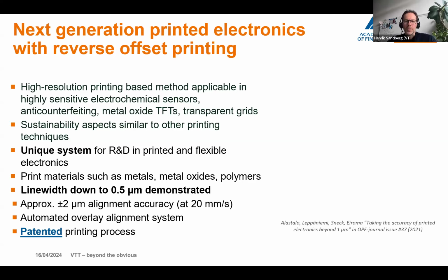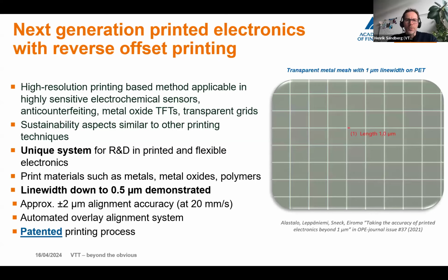The sustainability aspect of this method is similar to, let's say, other printing methods, and it's a very unique system, especially in Europe. And we can print metals, metal oxides, and polymers, for example, for insulating layers. We can reach even below micrometer accuracy, and also the overlay alignment is on the same level. That is just an example of a transparent metal mesh using silver on PET. So really fine lines, and the applications then can be anything where you need this kind of features.